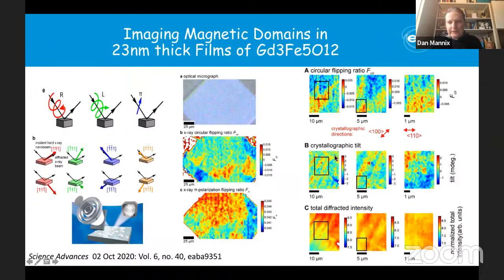We can also look at the crystallographic tilt information. It basically moves the Bragg spot onto our detector, and you can trace that back to some kind of tilting effects in the crystallinity of the material. So this is tilting in millidegrees that you get out. And these also seem to show some effects going along the 100 direction. That seems to be somehow subtly correlated also with the magnetization, these magnetic domains in the 100 direction.